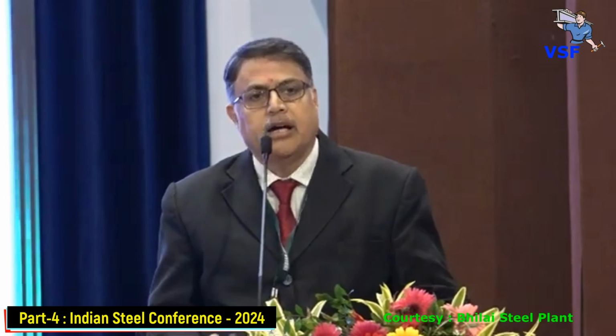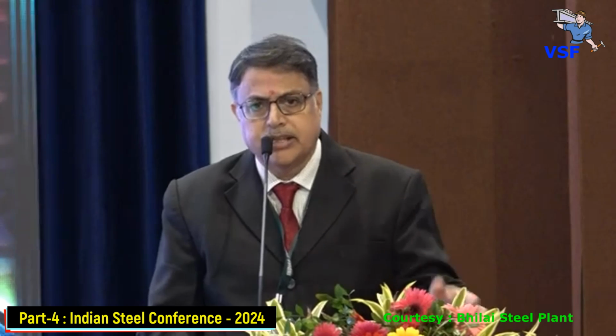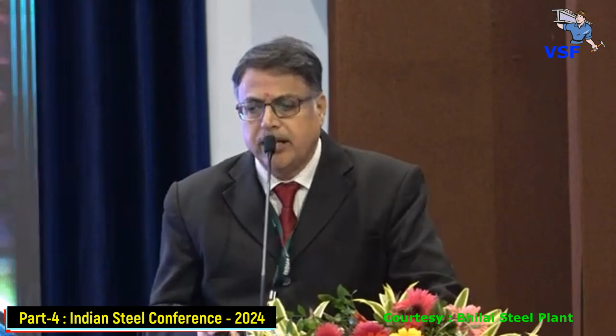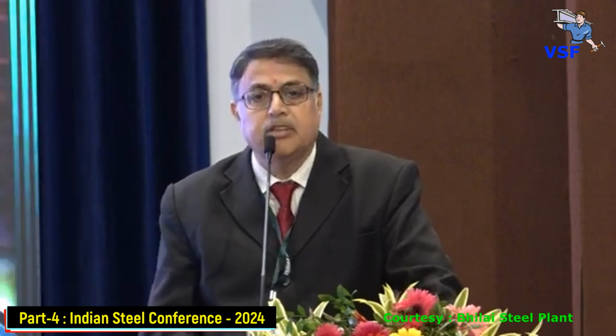which is basically something like a super absorbent polymer. As you know, typically in monsoon season you get very wet coal and wet ores, and therefore the flowability of these products is very hampered, and it affects production. Consequently, there is a production loss. So we have come up with a product to alleviate these problems. I am not getting into the technical details. Similarly, we have an organic binder which we have developed for agglomeration. This is for the pelletization and agglomeration process.